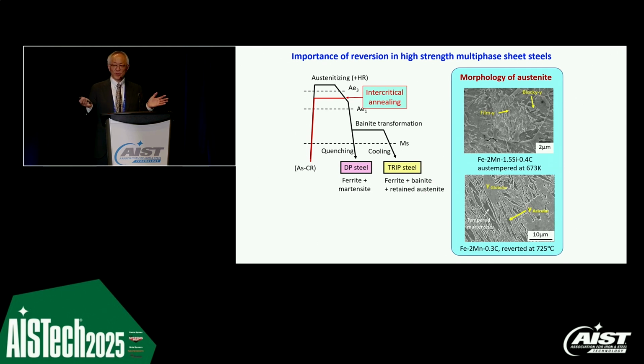Of course, now all of us know reversion is very important for high-strength sheet steels, for the intercritical annealing starting from the cold rolled sheet steel. For the hot rolling route, we have simple phase transformation in ferrite transformation, and by isothermal tempering, we have bainite transformations. So we have the characteristic retained austenite. And of course, the size really varies. It depends on the place.